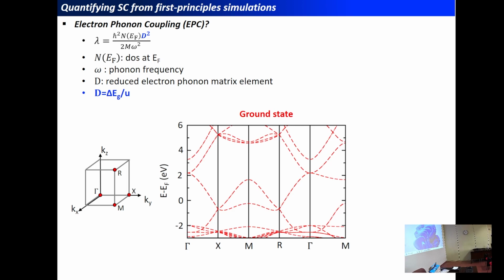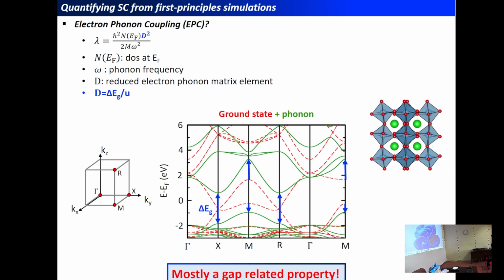So in the simulations, what we have to do, we take the ground state of the material and we look at the band structure without any lattice vibration in the material. And then we freeze some displacement associated with the phonon mode. And we look how the band structure is affected by the presence of the phonon, and we estimate the band gaps that open. So in the metallic state, these bands were touching exactly here, and through the lattice distortion, we see some gap openings appearing at the high symmetry points, and we can quantify the gap opening. And when we renormalize this gap opening with the amplitude of the lattice vibration, we get this reduced electron-phonon matrix element. And then we can compute this lambda for a given phonon at a precise q vector and k vector, momentum. So as you can see, to estimate this lambda, we have to quantify some gap in the material. And so it will be extremely sensitive to the magnitude of the gap we will quantify.